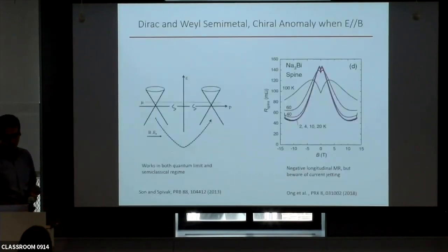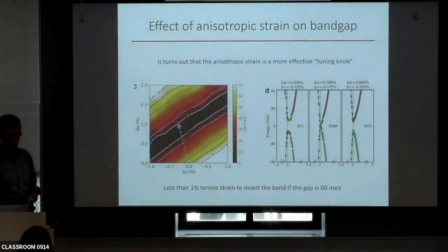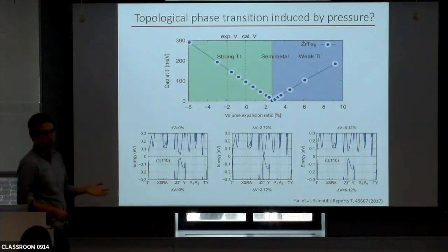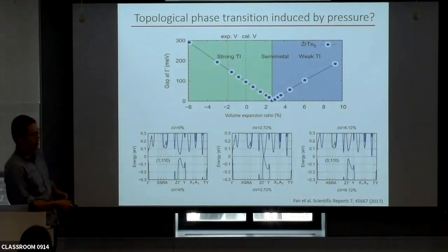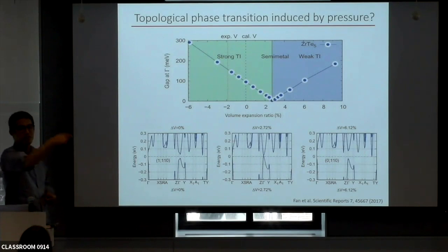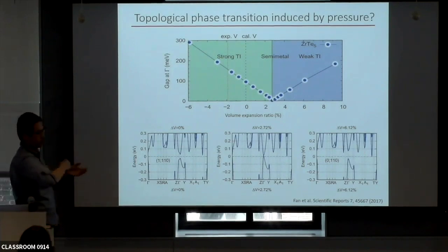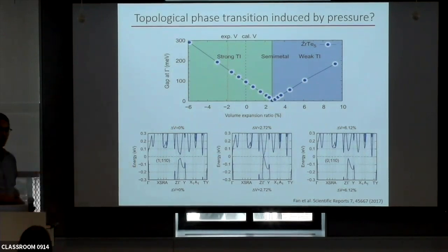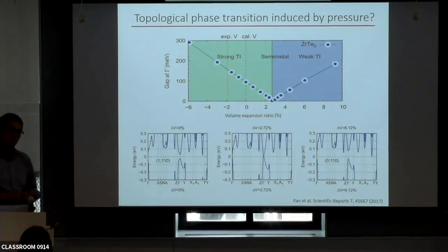But the problem is that when you go to more doped samples, which is usually n-type, it becomes more complicated, because when you go to n-type, there's this other indirect gap here, and then you introduce the second pocket, and then it's less clean as a function of strain. And if you're just focusing on the hole-doped side, then you see a very clean Dirac fermion.